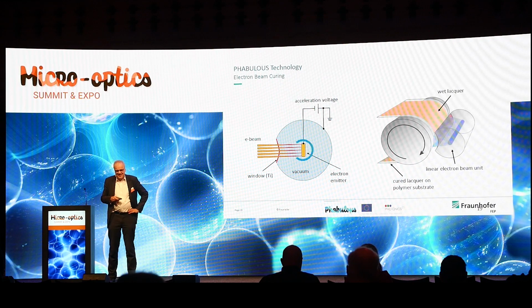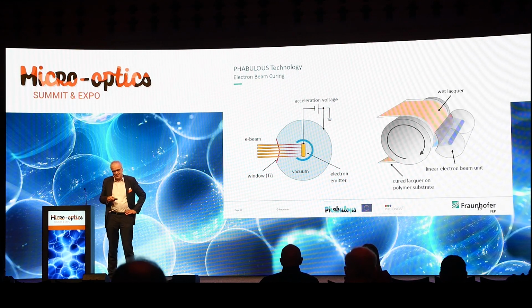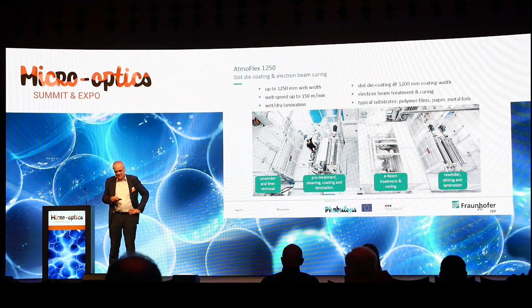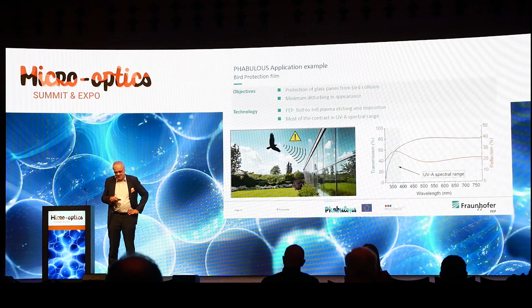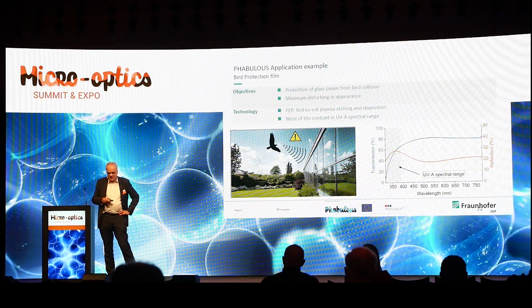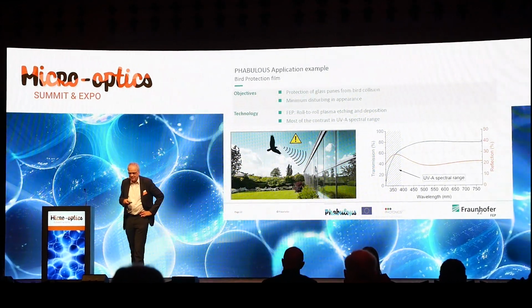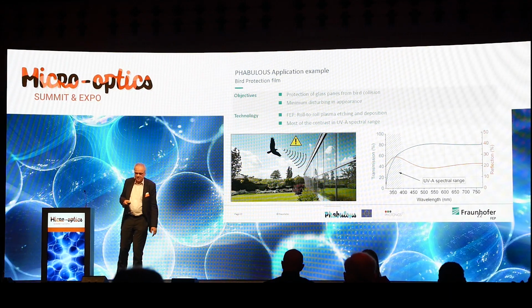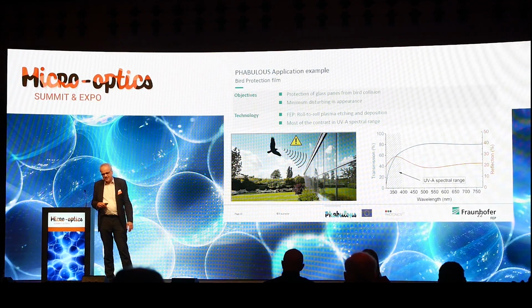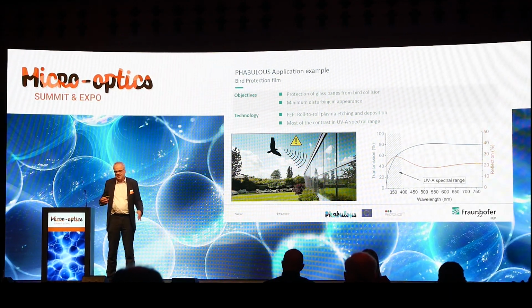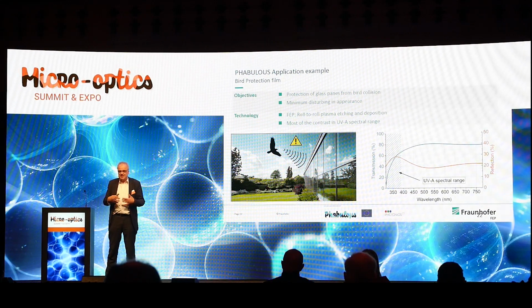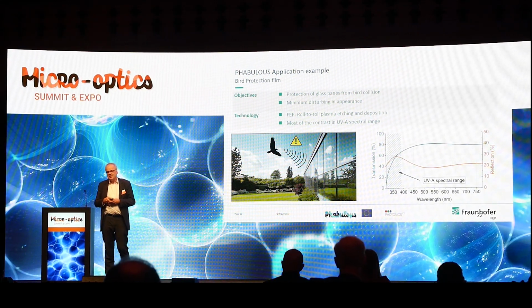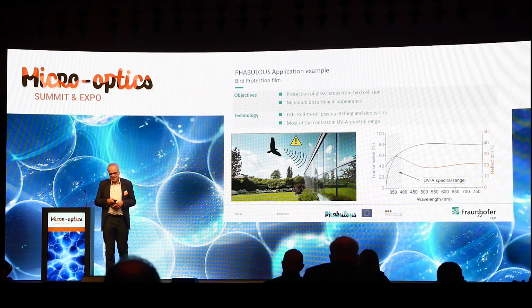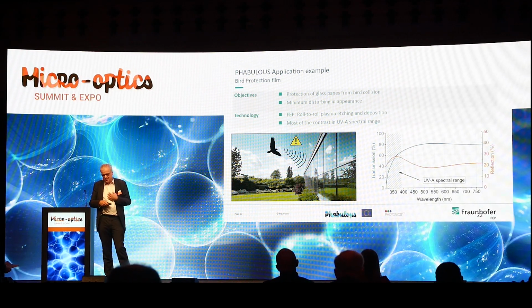Okay, good. Then I want to conclude with one slide concerning an application which I have shown you, which is a bird protection film, which has a different contrast in the UV compared to the visible light. So what we exploit is that birds see the UV and we do not. So that's why we could have put all the contrast in the UV.